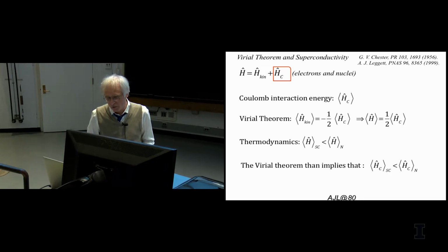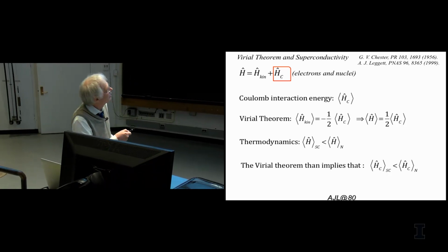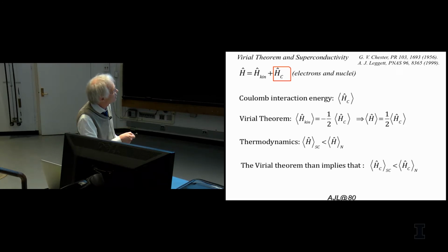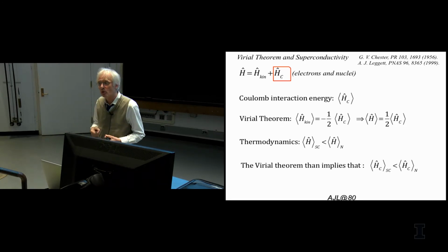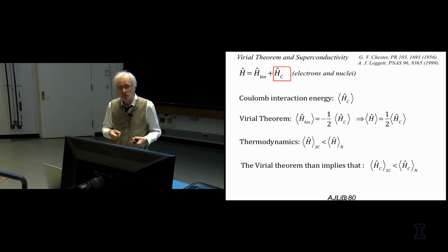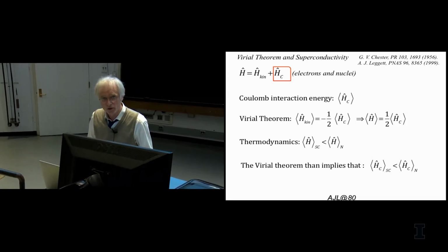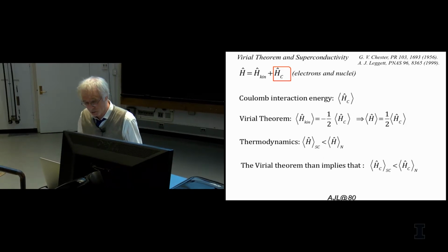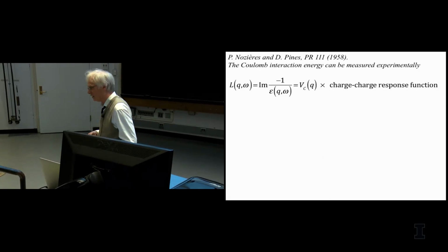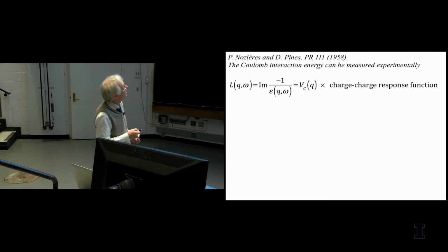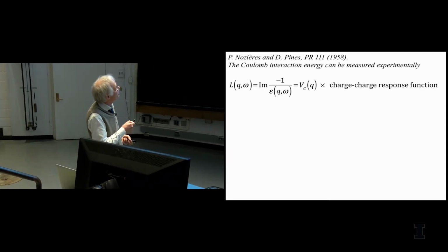Now if that is true, then it implies that also the Coulomb energy, which is just half this, should also be smaller than in the normal phase. In other words, the Coulomb correlation energy of your total system has to be smaller in the superconducting state than in the normal state, otherwise it would not be thermodynamically stable. Now the nice thing is that the Coulomb interaction energy can be measured. And that's actually because there's a nice relation between the charge-charge response function and the loss function that I spoke about. It's just the charge-charge response times the Coulomb potential in momentum space. That gives you the loss function.